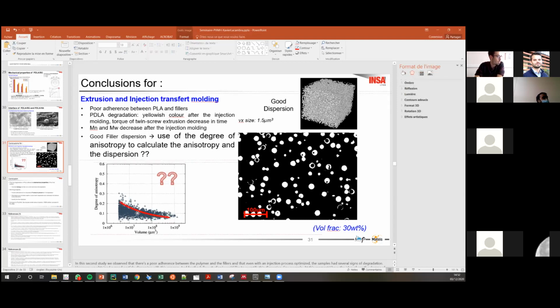Okay, because actually, if there is no anisotropy, it should converge to 0. So the fact that it's not 0 means that there is an anisotropy at large scale. Yeah. It's not exactly 0 you get at the end when you have the larger volume. Yeah, it's close to 0.1 for the injection transfer molding. So it means there is a slight alignment in one preferential direction in your volumes, but it's not so huge actually. Yeah, it's not so huge. When you see the ellipsoid of anisotropy, it's almost a sphere. Almost a sphere, so it's not very anisotropic. Yeah.